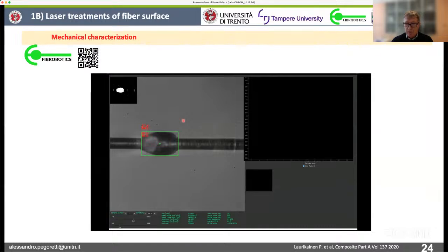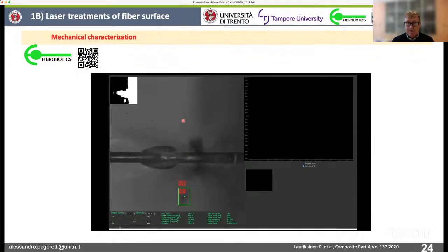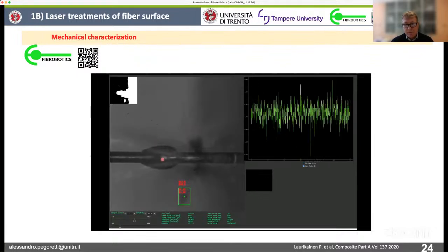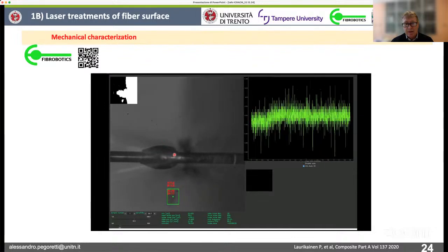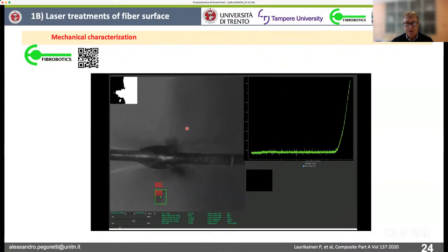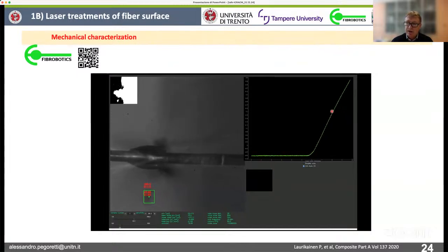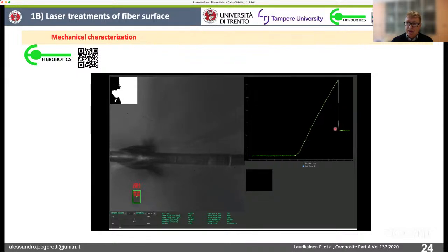Here is another movie in which you can see the test performed by the same machine. So after the droplets are deposited on the fibers, it is possible to test the fibers by performing the pull-out, the micro-debonding directly in the testing machine. Now the movie started, so you can see basically the fibers which are moving, and now we reach a contact between these grips, and the force starts to increase until we reach a break.